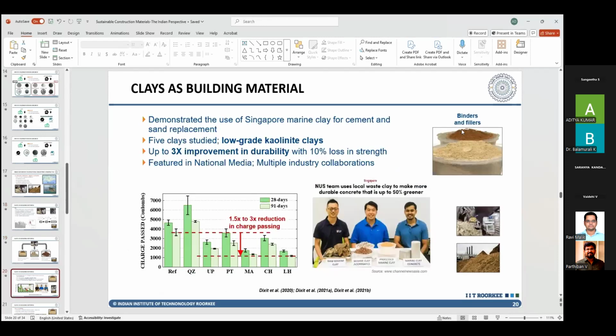And we studied about 5 different clays, different types of clays with different kaolinite content, and therefore different reactivity, because the more the kaolinite, the higher the reactivity. And we found that, depending on which kind of clay we are using, compared to a normal OPC-based concrete or mortar, we were able to get up to 3 times improvement in durability, which was measured using the rapid chloride permeation test.